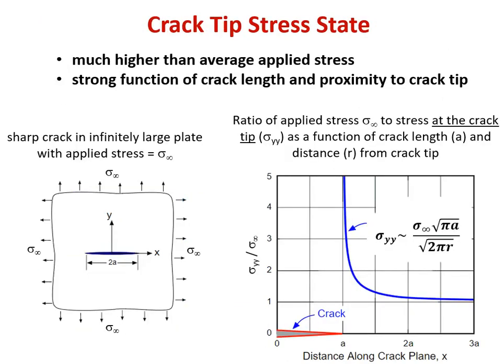Okay, so that was it for energy mechanisms. Main takeaways being, to advance a crack, we dump energy into the system, mainly taking the form of elastic strain energy, similar to what we saw around dislocations and solutes. That can then be apportioned to creating a surface or to moving dislocations and other plasticity mechanisms.